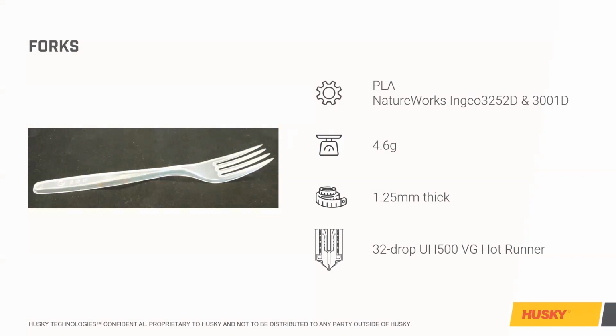Next, we have some application examples that we have running in the field right now with some of the bioresins available on the market. So this is a fork application. We've done quite a bit of cutlery over the last, I would say, 15 to 20 years. PLA is one of the first bioresins that were available in the market. It has this specific application. We're looking at a 4.6 gram part weight, about 1.25 millimeter thickness, and this was a 32 drop valve gate system. System ran with no issues.